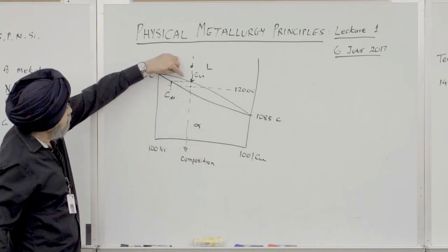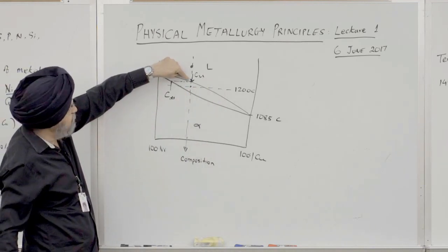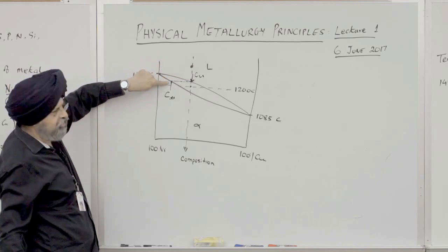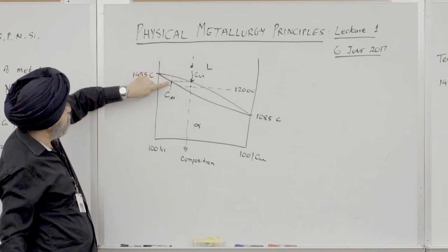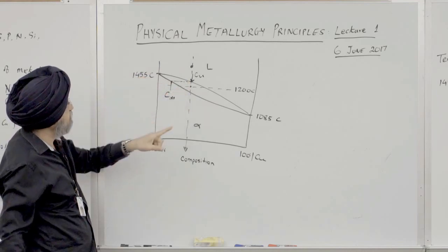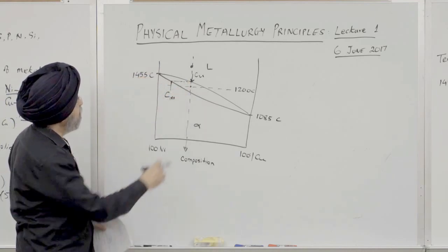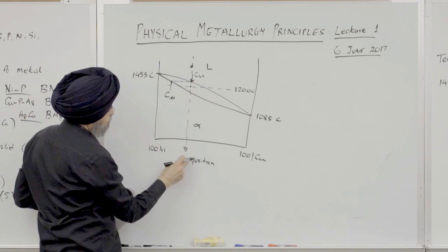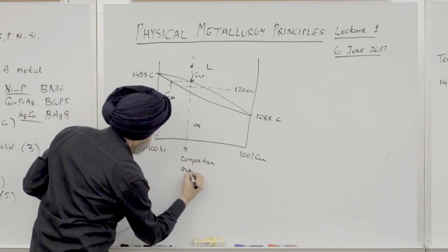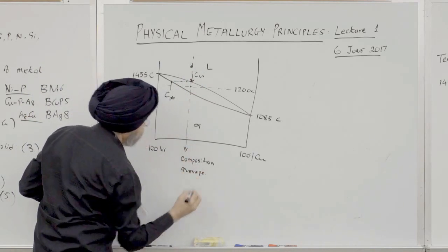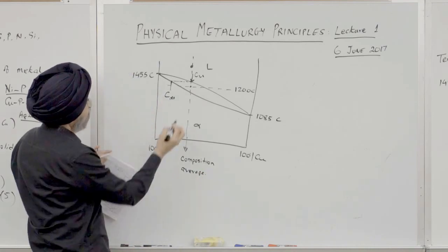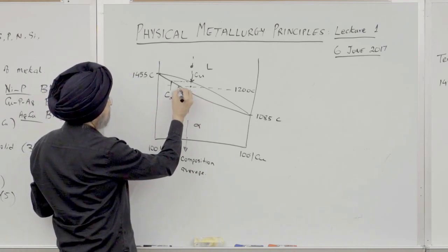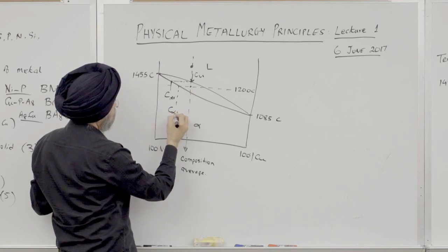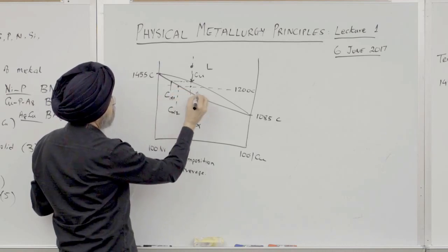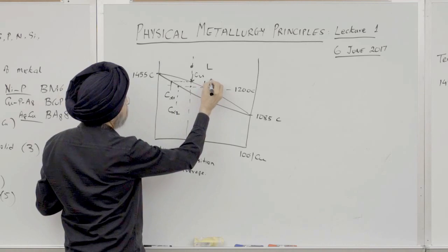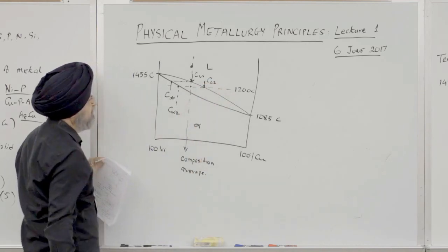So just at the point where the temperature was on the liquidus, the first metal to come out has this composition, and the liquid has that composition. So the liquid composition is almost the same as the average composition of the alloy, right? When I get to this point, this is now the composition of the solid, and this is the composition of the liquid.